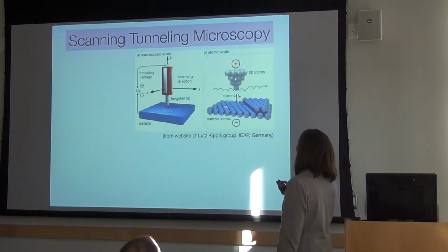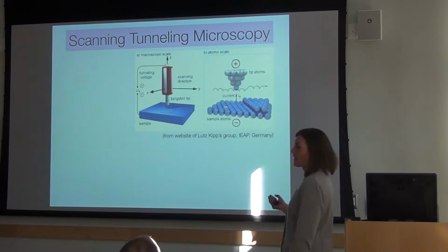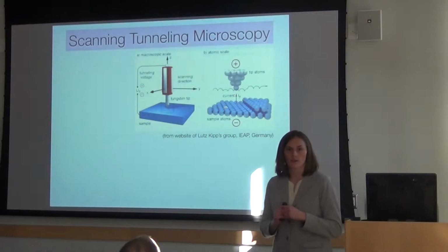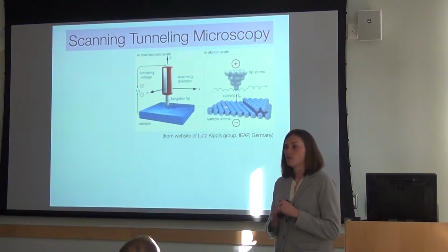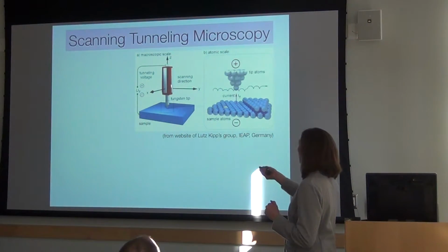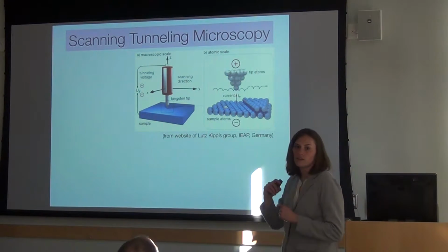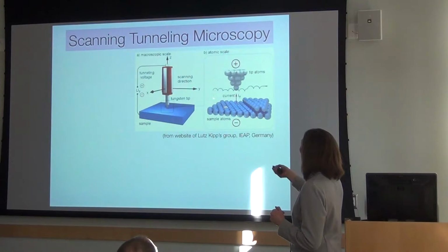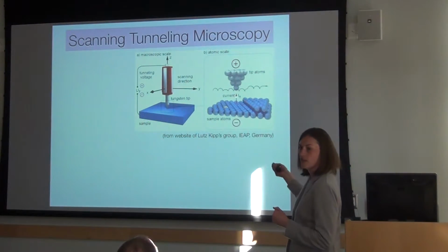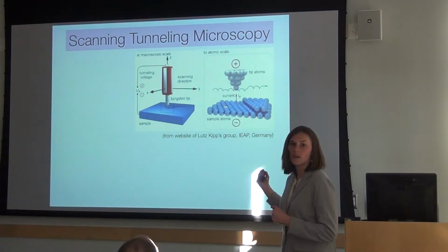So it's always this convolution of electronic properties and topographic properties that you're measuring. In reality, what we do is we have a feedback loop that holds that tunneling current constant, and then we control the height of the tip using the Z piezo. So the tip actually moves up and down and up and down and up and down across the surface as we scan.